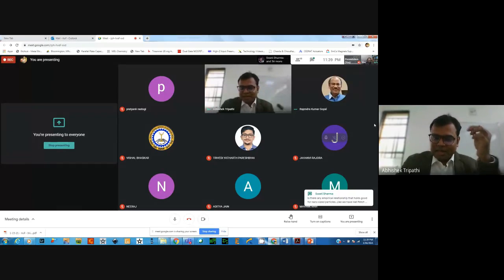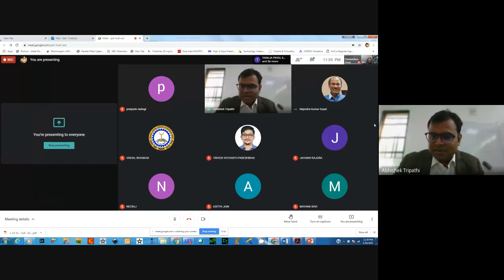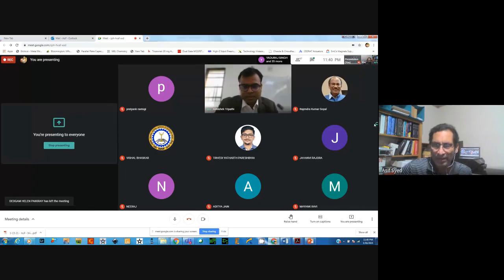We have another question from Rasdeep Bhattacharya. He's asking, since we are dealing in nanoscale, are there any visible variation to the results of the test performed? And if yes, how do we optimize such variations? Well, there will always be statistics. Everything is statistics, so you need to do a number of tests and then you can use the statistics to guide you. Because properties of the materials, when you try to measure, for example, if you take fused quartz and measure the hardness, most of the time you probably measure about 8.3, 8.4, about 9 GPa.